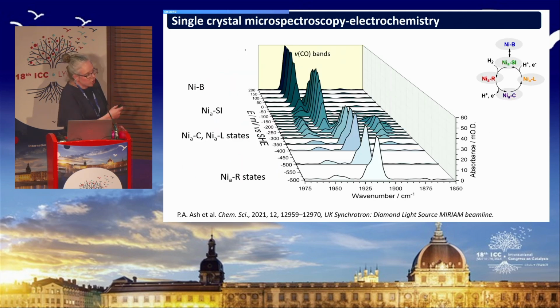And so we can record this sort of set of spectra as we apply potentials at the electrode, and we can think of this as a route map that allows us to map out exactly what potential we have to dial up to get any state we want in the hydrogenase active site within the crystals, and we're getting complete conversion of all of the hydrogenase active sites within the crystal into the states that are represented here in the spectra. And they're lovely intense spectra for a protein molecule, because within the crystal we have an effective concentration of about 8 millimolar protein, which is much more than we could ever get in solution. And so that gives us these very nice looking spectra.